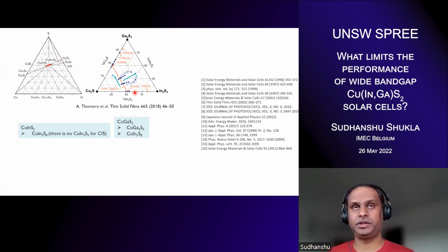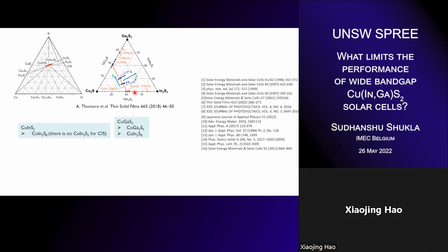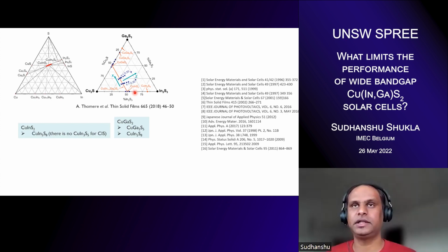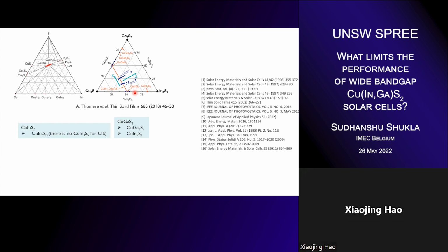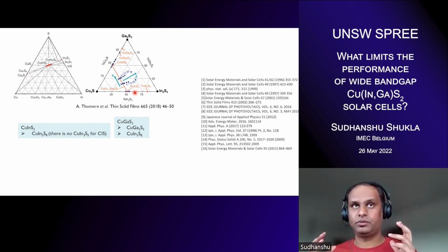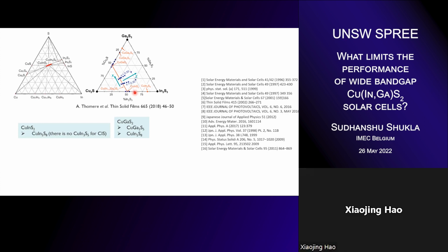Yeah, that's a very valid question. For kesterites, you have a high absorption coefficient, so you use less material in the end. But I would think that the absorption coefficients for the CIGS disulfides are actually not that low. So you can still go even thinner. And when you use them as a top cell in tandems, these cells can be more thin because then you have a bottom cell that will be absorbing the light. So I think they can be made much thinner. But right now we are making it thick because these materials haven't proven themselves yet. They are still in the stage of being promising rather than actually proven. So once we break the barrier of 1 volt experimentally, quasi-Fermi level splitting is fine, but once we get an absorber with 1 volt VOC, that will be something. Yeah, great. Thank you.